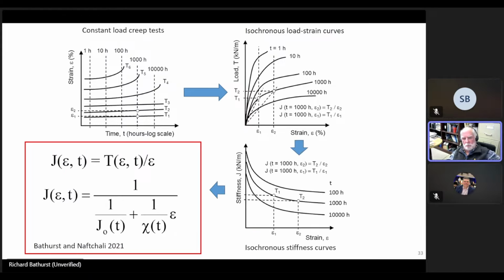This slide here shows the stiffness of the reinforcement as a function of time and strain, and this hyperbolic model that I showed earlier can be simply rearranged in order to show the influence of strain level and time on the stiffness of the reinforcement. So you can see the stiffness here is proportional to the load divided by the strain. And it's this stiffness model that needs to be used in your numerical model.